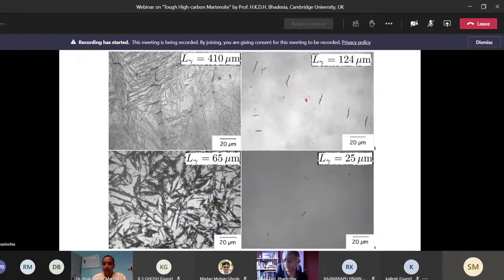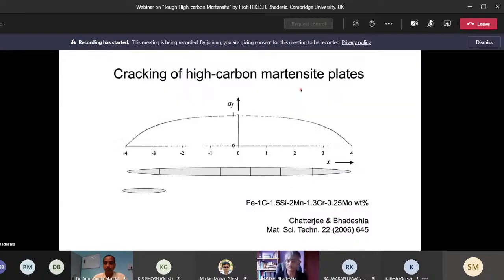Okay, so if I make my austenite grain size somewhat smaller than the distance between these cracks, then these plates of martensite will not break. Now, why is that? What is the reason why the plate tends not to break if you make its length much smaller? Well, if you look at composite theory, where we put short glass fibers inside a matrix, then when you get to a certain length of glass fiber, which is small enough, you will not be able to benefit at all from the presence of the glass fibers inside your polymer matrix. This is because it becomes impossible to transfer stress onto a small fiber, all right? And that's illustrated over here.